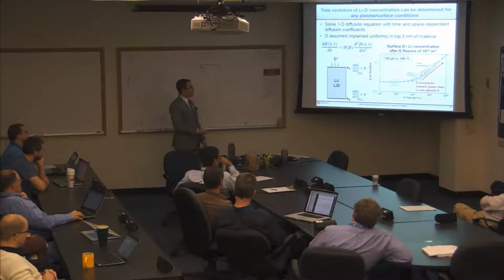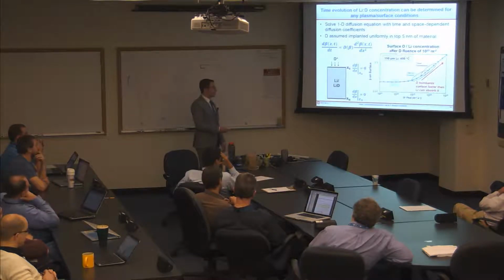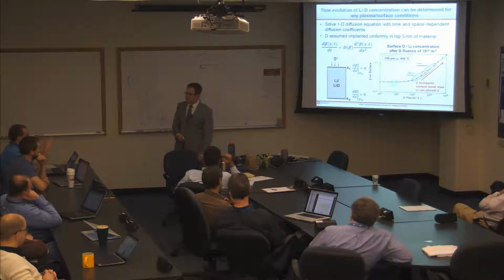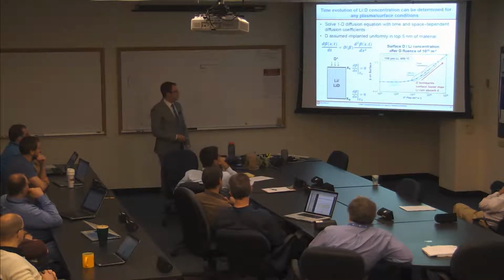The experiments I'm going to show you are in this range of flux, and the predicted fluxes in the divertor of a fusion reactor are down here. There is some overlap between the two. That's for a constant fluence for each of those data points? Yeah, it's 10 to the 23 per meter squared for each one.